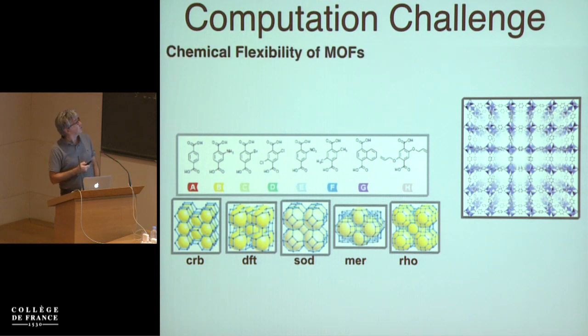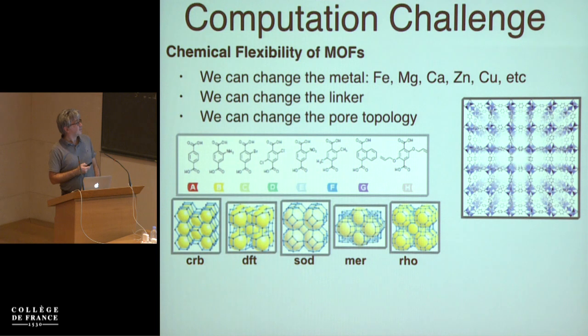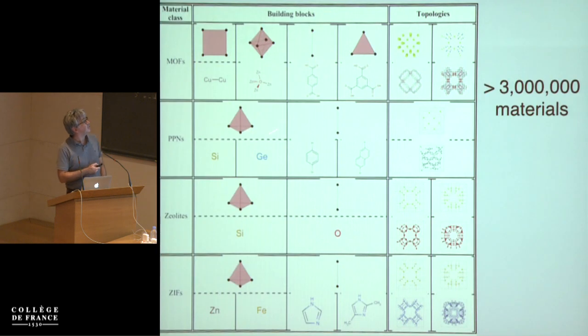So what we then try to do is basically use these nets, use these building blocks, and here you see them with 3. And we basically enumerate all possible crystal structures. And then we generate the crystal structure in silico. We use quantum chemical techniques to optimize the structure, and this is something we call a predicted structure.